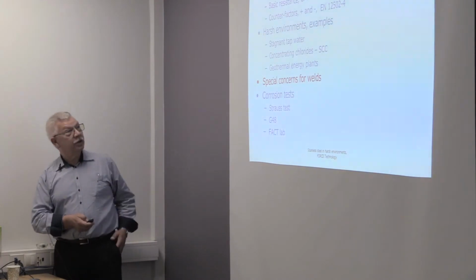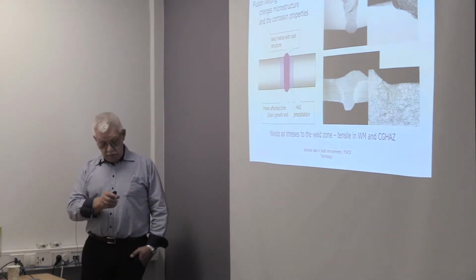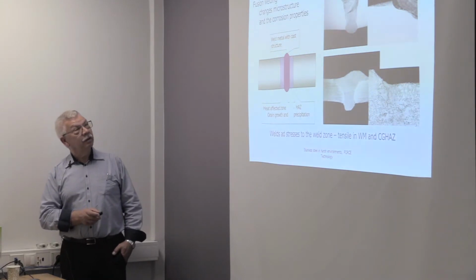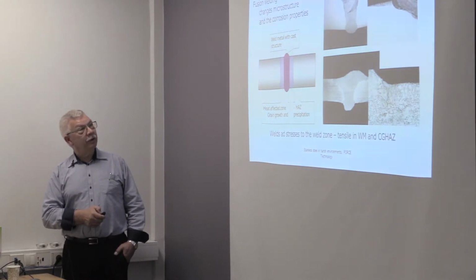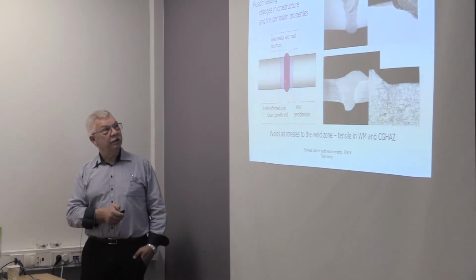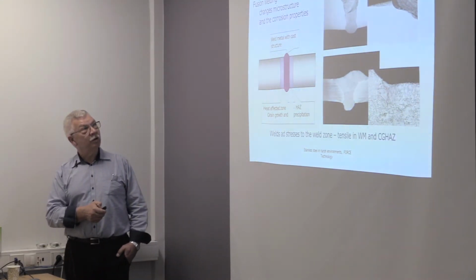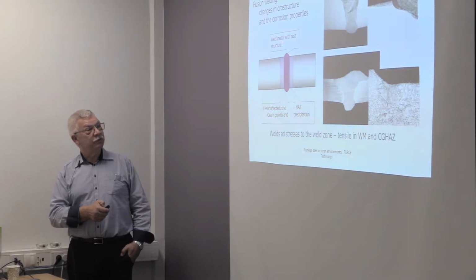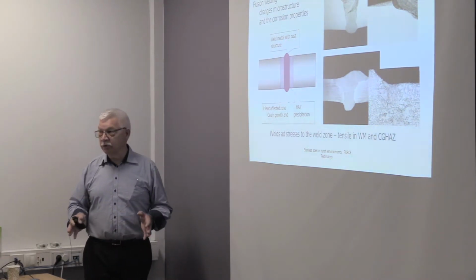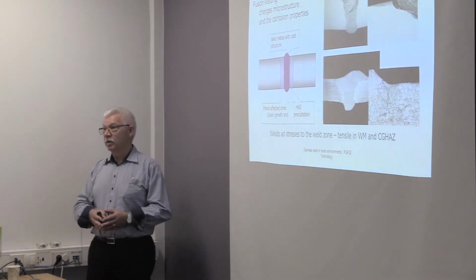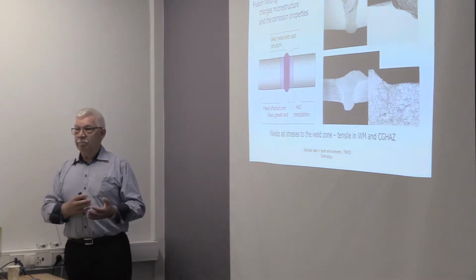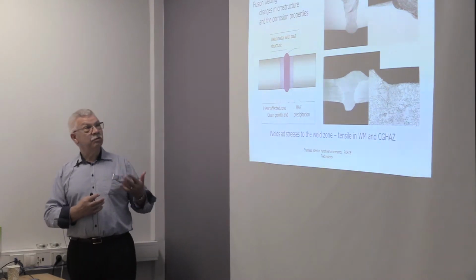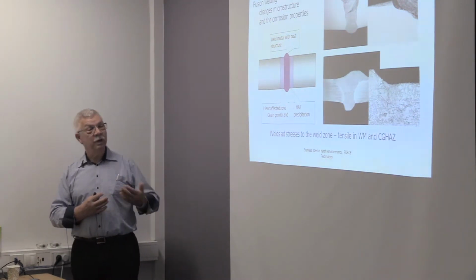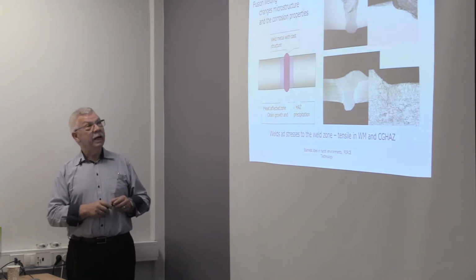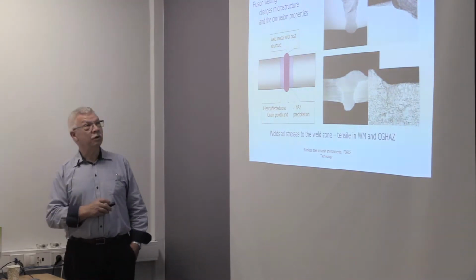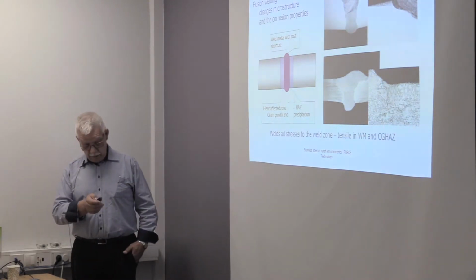About the special conditions for welds: in ordinary arc welding, where we have a material which is melted and solidified, we will have a cast structure. And a cast structure means that we, to some extent, will have a distribution of alloying elements. Chromium will not be the same in this structure. There will be areas with higher chromium and lower, the same for molybdenum, and that will affect the corrosion resistance of the weld. I will have an example in a little while.